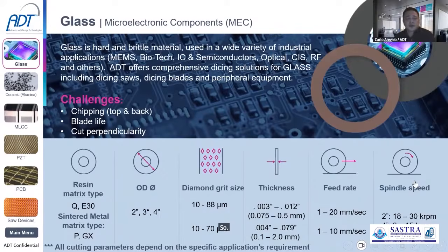So there are two types of blades that are recommended for this application for glass. You could do it with a resin blade. Also, you could do it with a sintered metal blade. The grit size for both of these blade types would range from 10 to 88 micron, 10 to 70 if you're using a sintered blade. The thickness range for the resin would be from 75 to 500 micron, and you can do it with a thicker blade because a sintered blade can support a thicker blade. So if you're using a sintered blade for this, it's 100 micron to 2 mm.